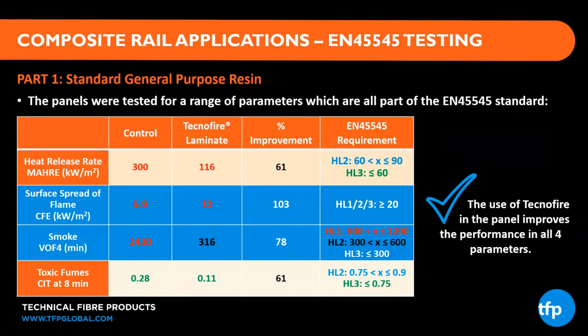So if we start by looking at heat release rate, and obviously a lower number is better in terms of heat release rate, the control, not surprisingly, has a very high heat release rate of 300 in terms of MAHRE, which is the maximum average rate of heat emission to this standard.